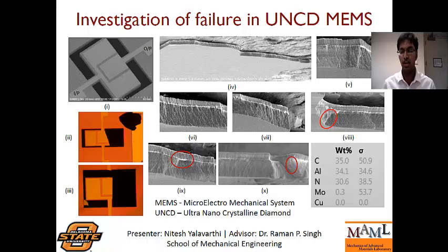be investigated. Further investigating this failure with the help of scanning electron microscopy technique, popularly known as the SEM technique, which allows you to look at devices even up to a nanoscale. We can see in the slide from figure 4 to 10, we can clearly observe the failure pattern from left to right respectively. Especially in figure 8, we see a cluster formation as marked with the red circle, which indicates a defect. When closely observed at this cluster, we see small voids which represent defects in the ultrananocrystalline diamond.